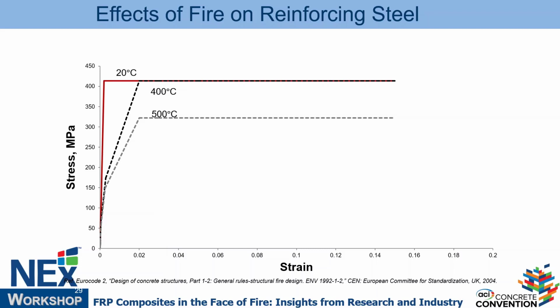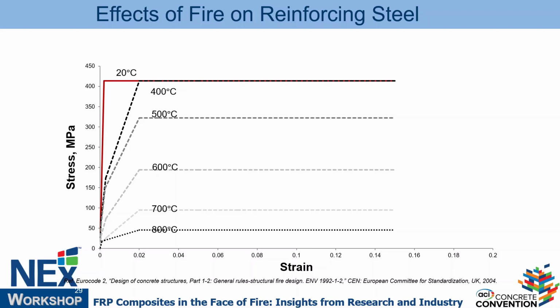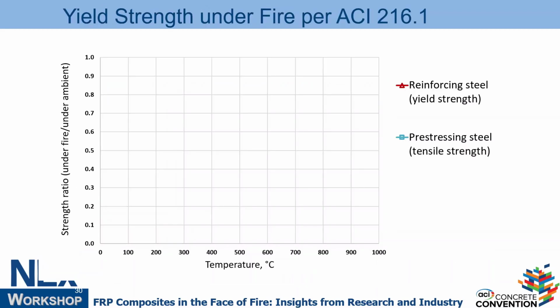Why is this considered critical? Because in general, the assumption is 50% is the minimum you need to at least support the dead weight of the structure, right? So that's why it's considered relatively critical. And then 600, 700, and you can see it starts falling apart. If I take the peak of each of these data points and plot it again, I can get the curve that represents the strength degradation with temperature. So this is percentage of the yield strength. So let's say it's 60 KSI, 420 MPa steel. Start there and start dropping as the temperature rises, right? So this is mild steel reinforcement.